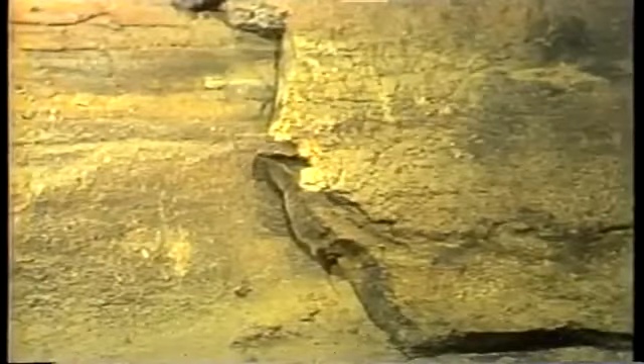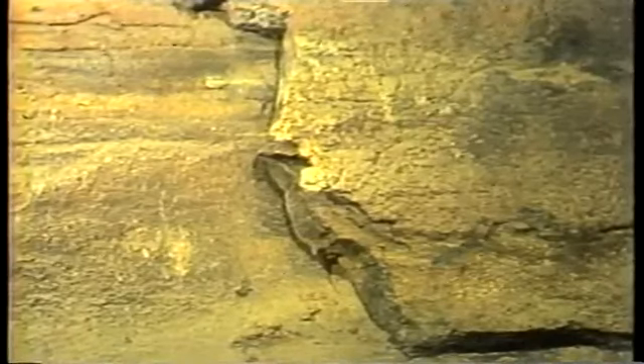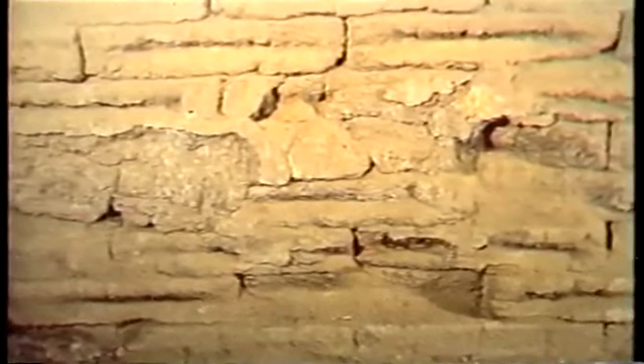Refractory has other potential problems: spalling, cracking, and slag attack. Spalling is the flaking away of refractory. It's caused by improper installation of refractory, by sudden temperature changes, or both. Cracking is due to improper installation or sudden temperature changes. Slag attack is the chemical reaction of ash and refractory. Slag attack erodes refractory, reducing its thickness. It melts the refractory and causes it to run off. Slag attack may also cause refractory to become soft and crumbly. In some cases, slag attack will produce a glassy surface.